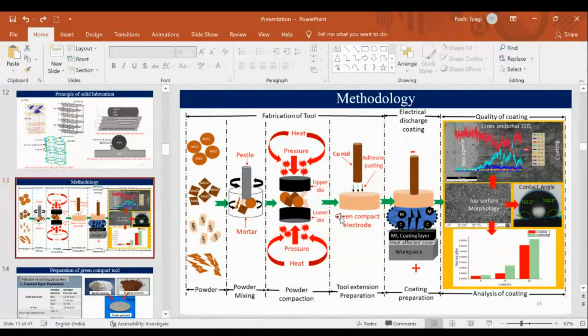The reason we are talking about green compact is that melting of the material doesn't take place, because we apply a temperature below the melting point of the powder. So then we obtain the green compact tool.